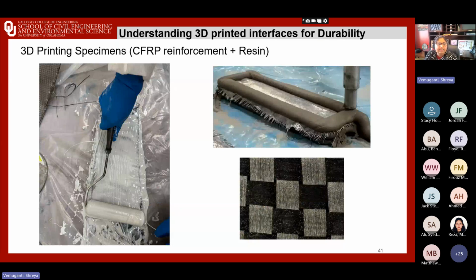This again is the CFRP, but with resin, just like we did for the GFRP. If you can see here, this is that rolling process. When you dip the fabric in the resin, it's purely saturated, right? You don't want so much excess resin in those interfaces. So we are essentially using rollers.